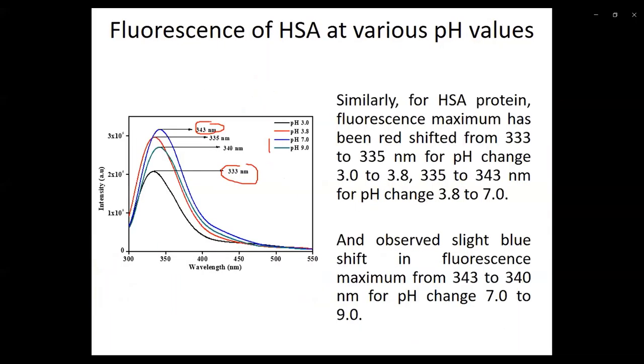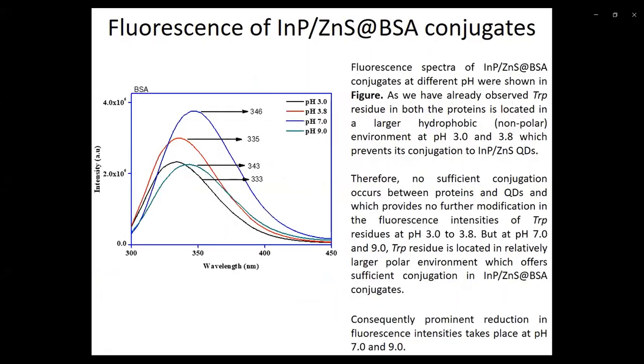Similarly, this spectra shows fluorescence intensity of HSA prepared at various pH values. Intensity has increased as pH increases from 3 to 7 and a red shift in the peak position is observed. Later, from pH 7 to 9, a reduction in the fluorescence intensity and blue shift in the peak position was observed. Later, we mixed BSA and HSA proteins at various pH values with QD and recorded their fluorescence spectra, and we observed a drastic reduction in their fluorescence intensities as compared to the pure BSA and HSA proteins.